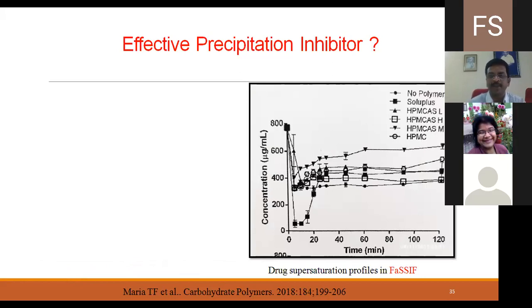Now, when we come to the fasted state simulated intestinal fluid, the solubilizing effect of Soluplus on the drug was drastically decreased in the biorelevant medium. That is because some studies have reported an interaction between Soluplus PEG repeating units, protons, and the negative charge of SLS. This is the reported example. Because of this interaction, a complex forms, which can either increase or decrease the dissolution of poorly soluble drugs. Lecithin and sodium taurocholate are present in the medium, and they have amphiphilic structures comparable to SLS that can interact with Soluplus in the same manner. Because of this interaction, there is a decrease in the effect seen here.